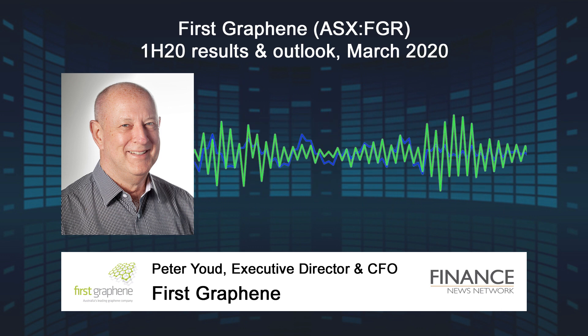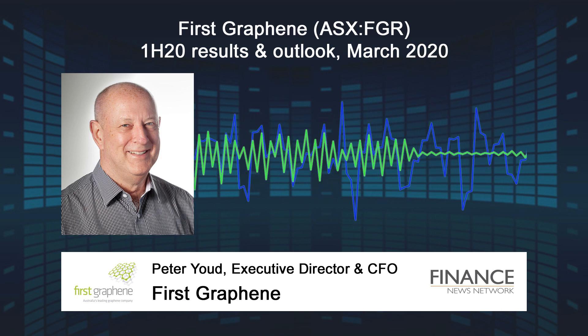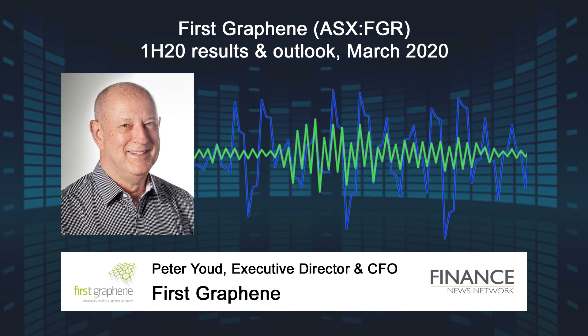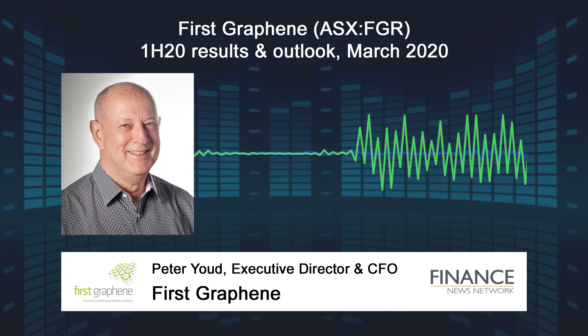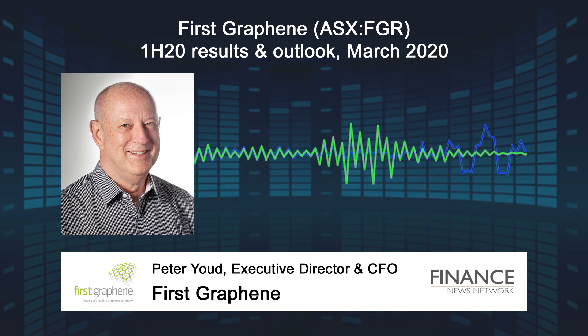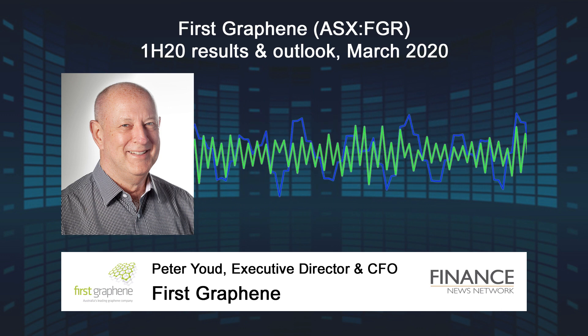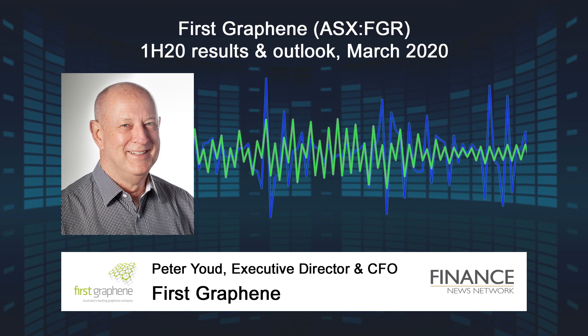This has included hot-cast PU wear linings for the mining market, and TPUs for both the mining and safety boot markets. In these areas, we see improvements of 40% in tear strength and anywhere between 100% to 500% in abrasion resistance in items such as pipe spool applications. We are now starting to work on the incorporation of graphene into traditional rubber formulations.